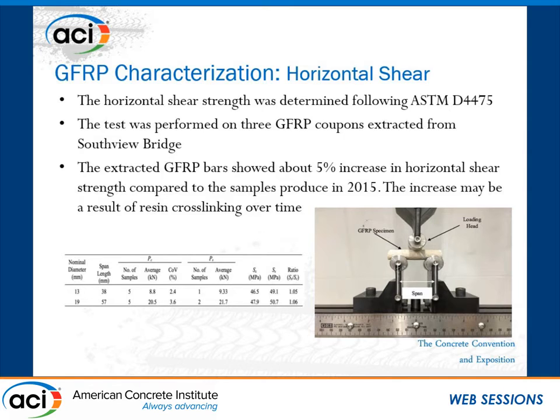One of the most interesting ones for us was the horizontal shear strength. This plays a really important role as an indication of durability, because horizontal shear, as you can imagine, deals with the mechanical properties at the interface of fibers and resin. With any kind of degradation, we can see it at the interface, and then the loss of bond between the fibers and resin, and eventually losing the load-carrying properties.